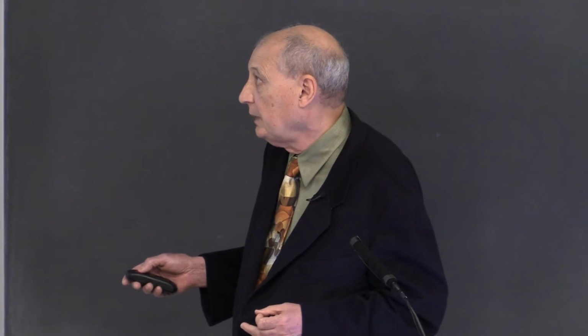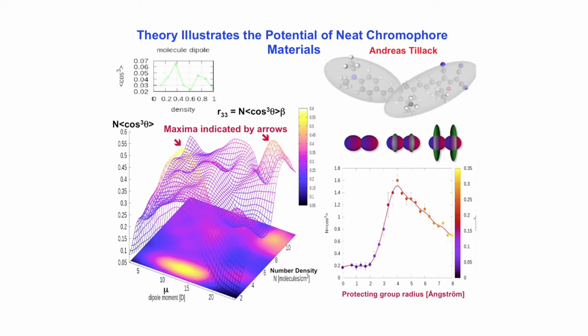both by Andreas Tillack theoretically and shown theoretically by Alex Jen and my group and others, you get this second maximum at high number density. So you get one maximum at low number density down here, you get the second maximum in the electro-optic activity at higher number density. And you also get two maxima in the acentric order parameter.